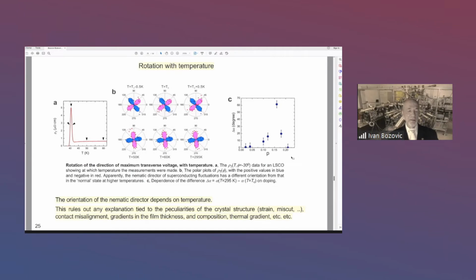Another important test is the temperature dependence of the amplitude and orientation of nematicity. What you can see is that C4 symmetry is broken already at room temperature, and that implies that the resistivity tensor is always orthorhombic, even though the films are tetragonal. But as or more important, the orientation of the easy direction, the direction of the highest conductivity, is not aligned with the crystal axis. And it even rotates with temperature. And that shows that the anisotropy that we observe in transport is essentially uncoupled from the lattice. That means that it is purely electronic.